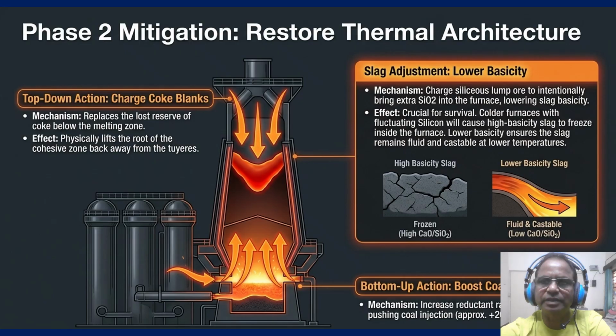The so what factor is survival. In a cold furnace, high basicity slag will freeze inside the furnace, blocking flow. So lowering basicity ensures the slag remains fluid and castable even at low temperature.